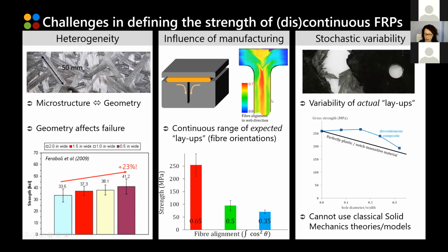So, for instance, while in a quasi-isotropic laminate, as we have talked about before, you would have discontinuous ranges of fiber orientations in the different plies, in discontinuous composites you actually have a continuous range of the expected layups or the expected fiber orientations that you have at each point. In this plot below, you can see some measurements that were done for discontinuous composites with different types of fiber alignment, going from the fibers more aligned with the loading direction in red to the fibers more aligned with the transverse direction in blue. But we basically have a continuum of different properties in between these three columns.